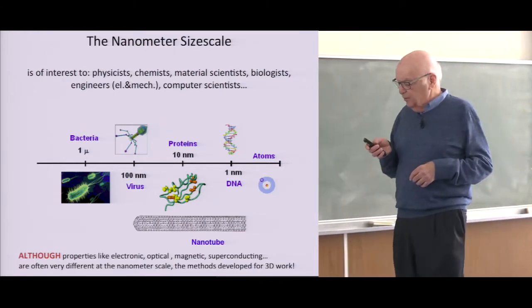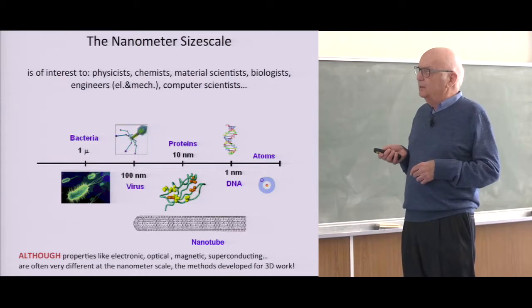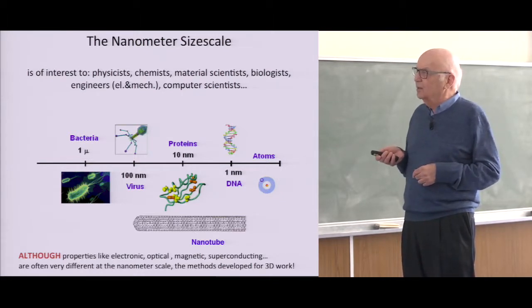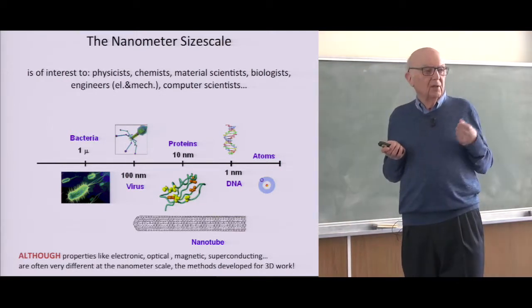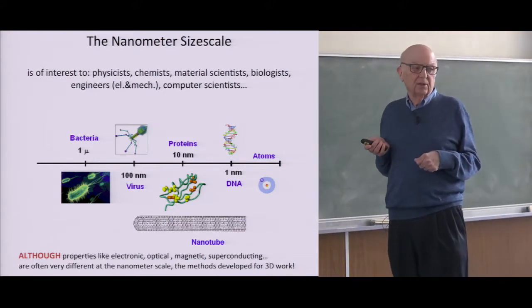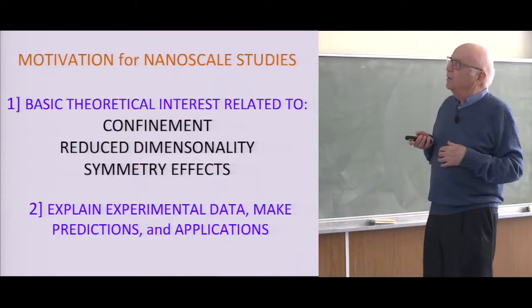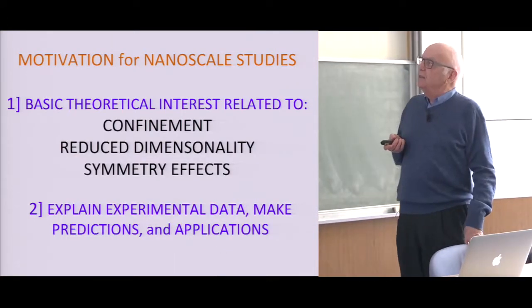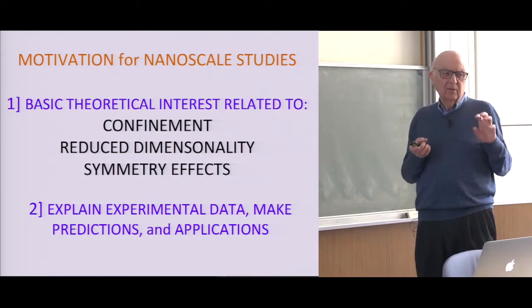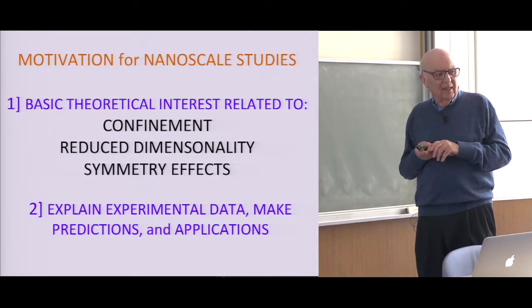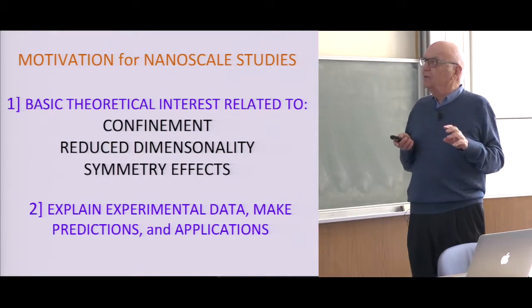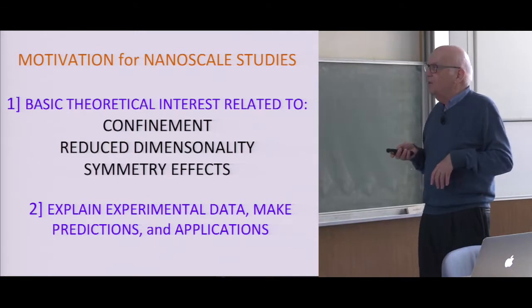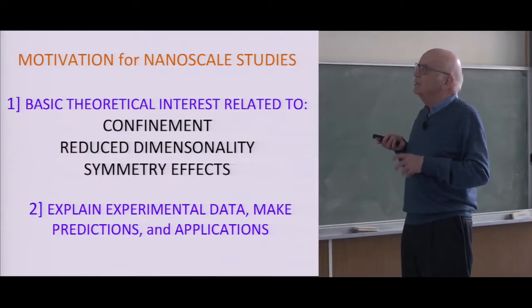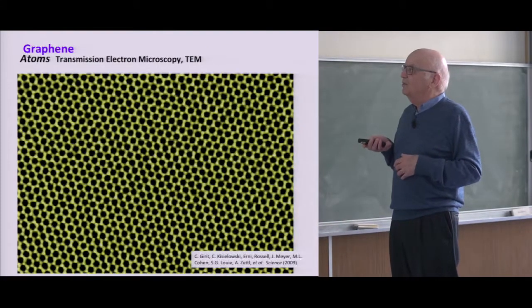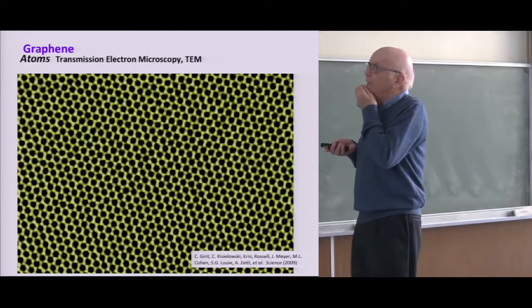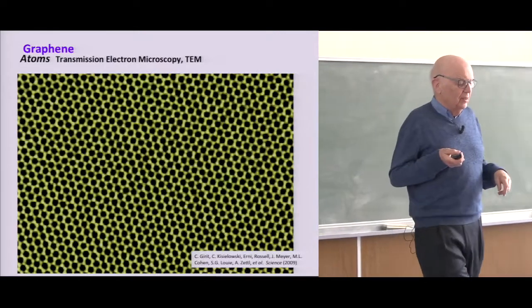And then from a theoretical point of view, there's a couple of comments. First of all, although the properties on the nanoscale, like electronic, optical, magnetic, superconductivity, are very different, the methods that I showed you that work for three-dimensional systems work in the two-dimensional setting. The motivation for studying these is that you get confinement. And when electrons are confined, they act differently. The reduced dimensionality gives you some really interesting effects, and I'll only mention a few, and the symmetry makes a big difference. So again, if you're going to explain experimental data and make predictions and applications, this is the other motivation. You have to be able to deal with these systems in such a way that you use the theory that was developed for 3D, and it works.